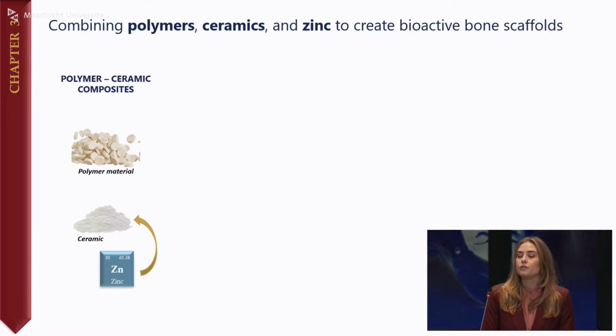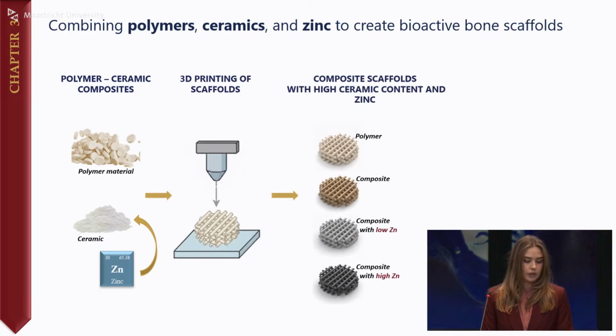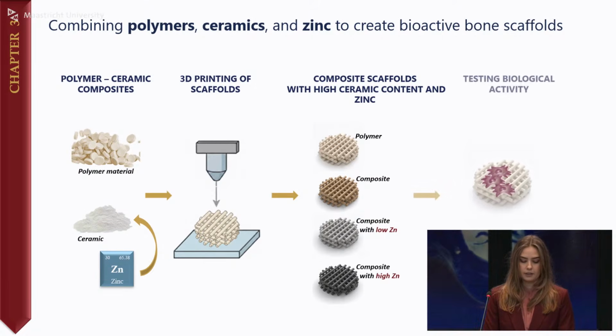To make the material even more biologically active, zinc element was added. Zinc naturally occurs in our bones and is known to participate in a lot of physiological processes involved in bone formation. Then we took this composite scaffold, we 3D printed it into three-dimensional porous structures with various compositions and different concentrations of zinc. And finally, we assessed their biological activity by culturing our scaffolds directly with stem cells.